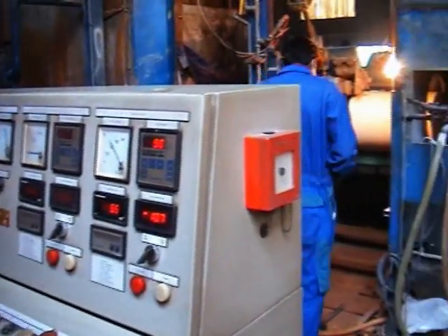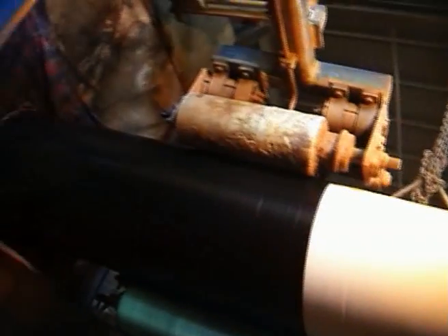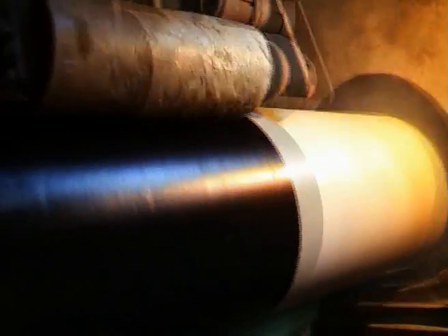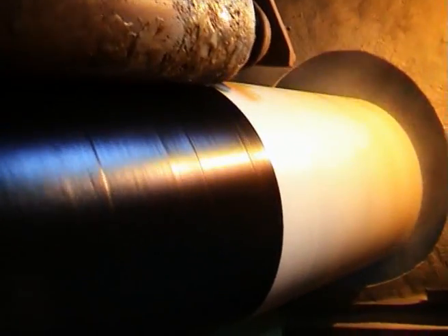Within a certain period, the adhesive film is applied onto the pipe by the pressure roller and wrapped around the rotating pipes. Adhesive thickness is maintained at about 360 to 450 microns. Immediately after the adhesive, the polyethylene final coating film is applied from the PE extruder through a flat head die and wrapped over the adhesive film.